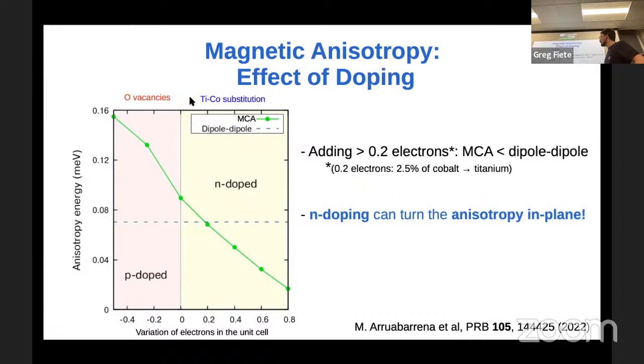For the magnetic in-plane, zero? This zero one. Yeah, so you go up and then you have the horizontal dashed line, right? Yes, over to the left. This is the dipole-dipole interaction, which mostly doesn't change with doping because it's mostly dependent on the local spin moments and how they interact with distance. So if you don't change the structure, it remains mostly constant.